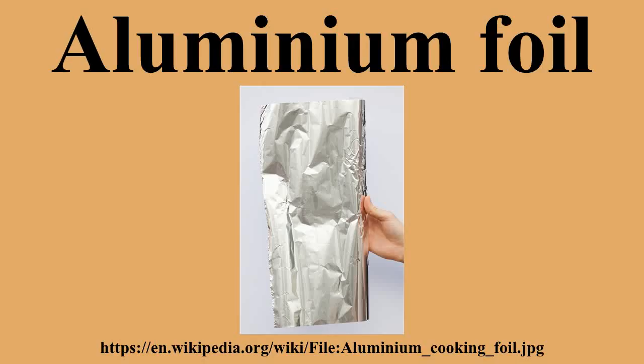Electromagnetic shielding. The shielding effectiveness of aluminium foil depends upon the type of incident field, the thickness of the foil, and the frequency. Shielding effectiveness is usually broken down into a reflection loss and an absorption loss. Although aluminium is non-magnetic, it is a good conductor, so even a thin sheet reflects almost all of an incident electric wave. At frequencies more than 100 MHz, the electric field is attenuated by more than 80 decibels. Thin sheets of aluminium are not very effective at attenuating low-frequency magnetic fields.